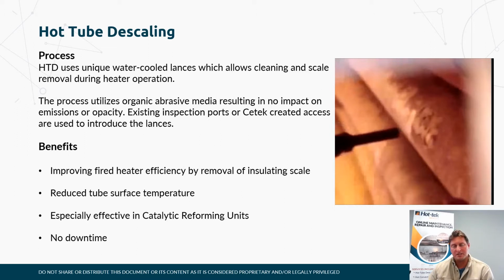So another thing that's important about the material selection or the media selection that we use for HTD is that it is an organic, and it combusts shortly after making contact with the process tube. So we're not actually adding any more material into the vessel. So the only thing that we're seeing is we might see some scale start to pulverize and move up through the stack. Heavier scale will land on the base, but again, no media from our impact will be left in the heater once we're leaving the process. So we have no downtime. We're able to remove the insulating scale, which is also going to be giving us false high temperatures of the tube.